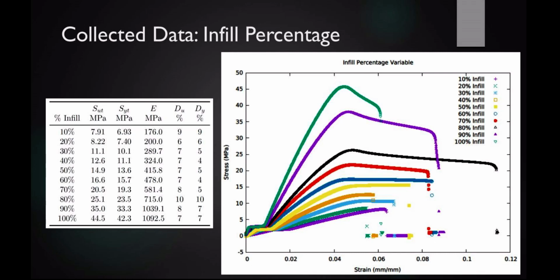100% is higher, but we see that it fails relatively early compared to the 90% one. It has a relatively low toughness. I should start at the start. We do see the toe region again, so that's a material property of the actual plastic. It's not really a structural thing. Then we have these lower ones, so below this line here. Again, they're all failing pretty early without seeing the full stress strain curve develop.